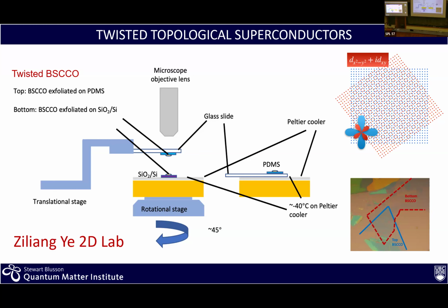And what you do, you approach one with the other. You approach the crystal onto a substrate that sticks to it. You pull back, and then you rotate your substrate by 45 degrees. The advantage here is that it's easier to do 45 degrees versus 1.1, which was the case of graphene. And so you come back down. And here is an optical image of what we obtained.